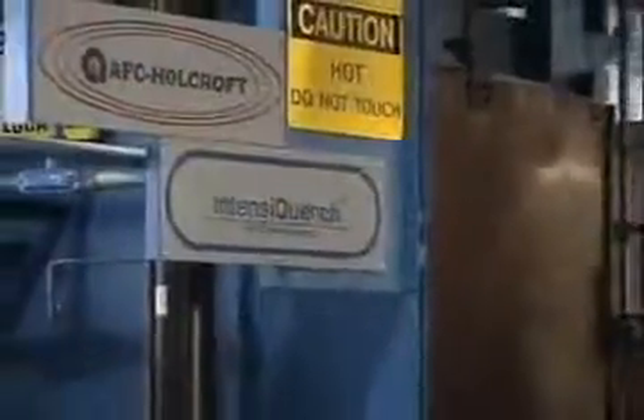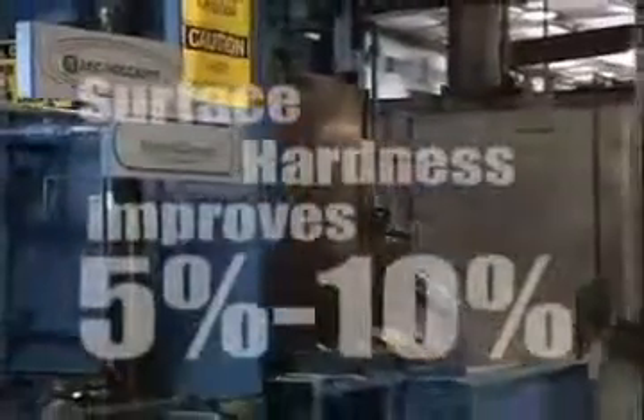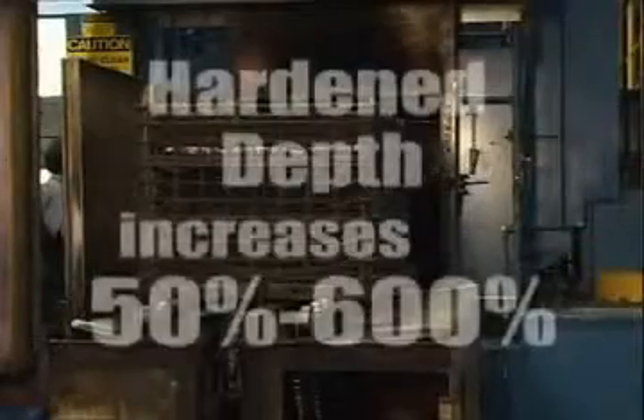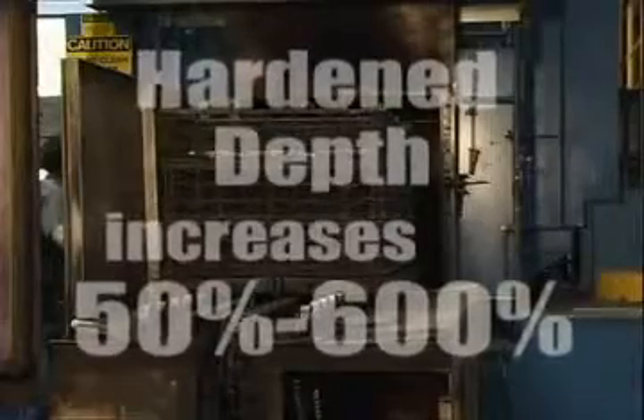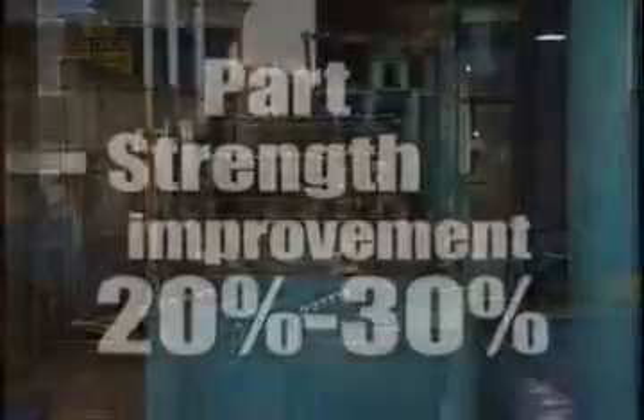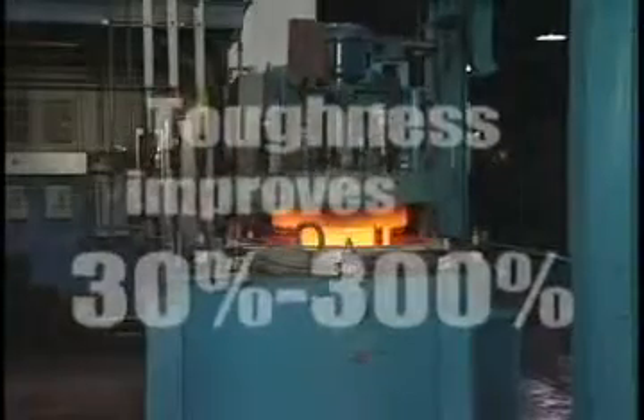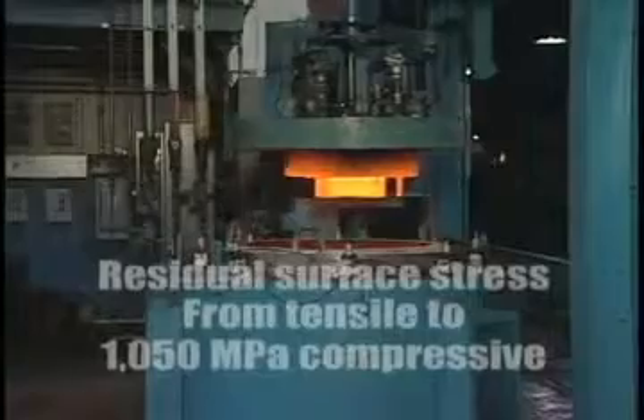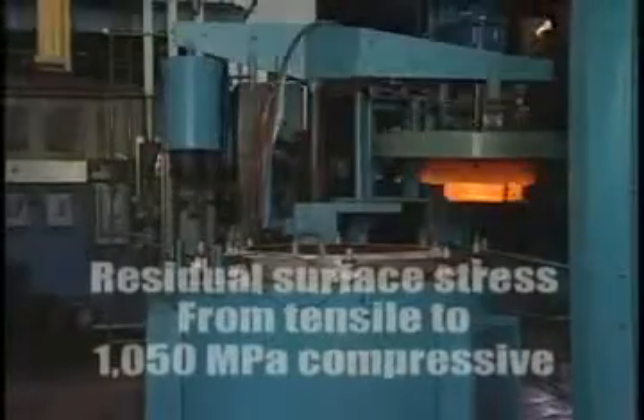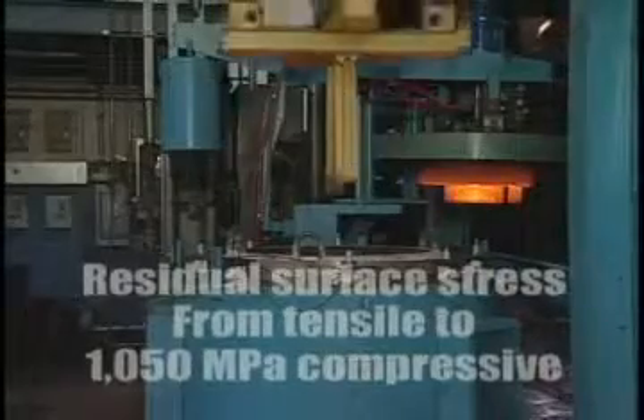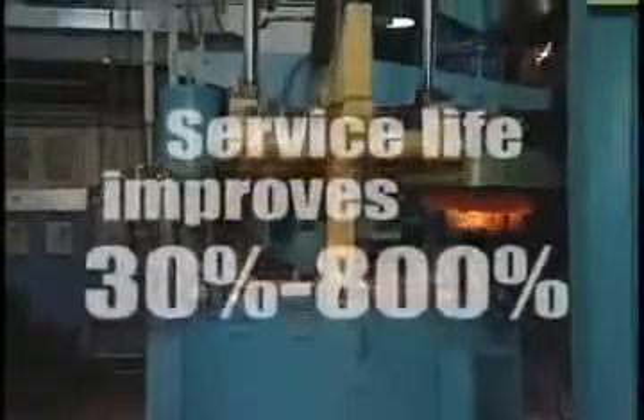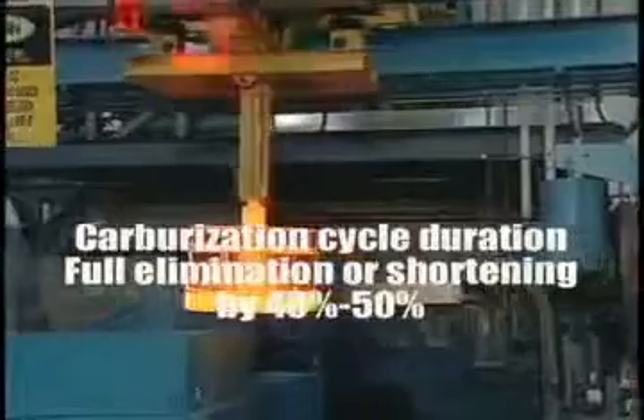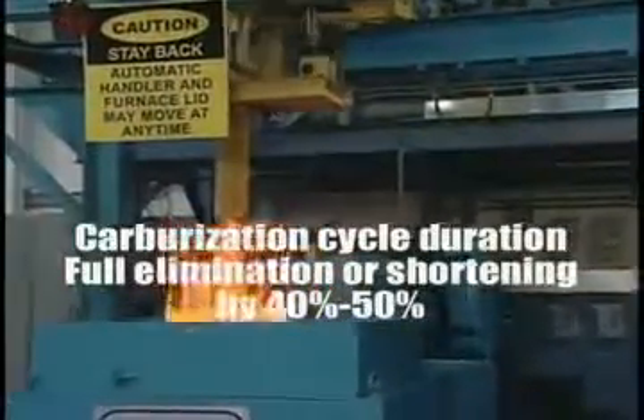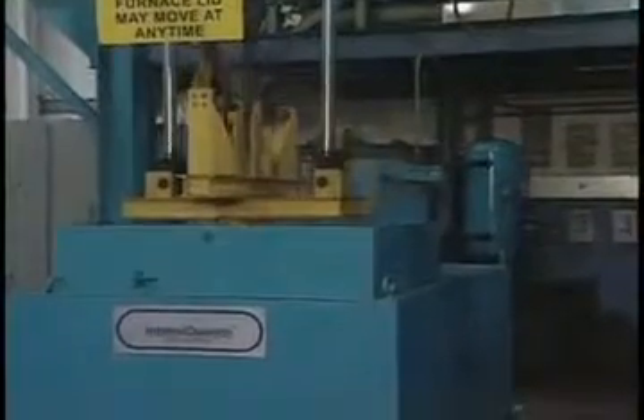IntensiQuench process proven benefits. Surface hardness increased by 5 to 10%. Core hardness improves by 20 to 50%. Hardened depth increases by 50 to 600%. Improvement in part strength is 20 to 30%, and improvement in part toughness is up to 300%. Residual surface stresses change from tensile after quenching in oil to compressive of up to 1050 megapascal after intensive quenching. Part surface life improved by 30 to 800%. Carburization cycle can be reduced by 40 to 50% or fully eliminated. Proven, IntensiQuench has made super strong parts.